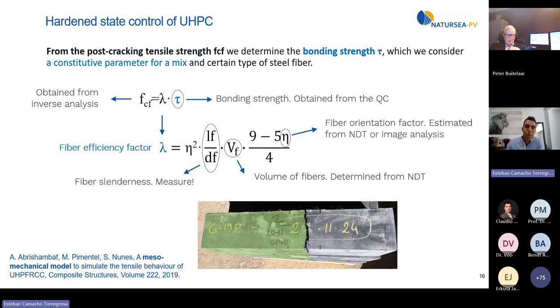And this depends on three things. One is the slenderness of the fiber. The higher the slenderness, the higher the efficiency, and we can measure the slenderness. I recommend you measure the slenderness of your fiber. Don't take what is simply written on the label. Measure the slenderness of your fiber. The second is the volume of fibers that you have.